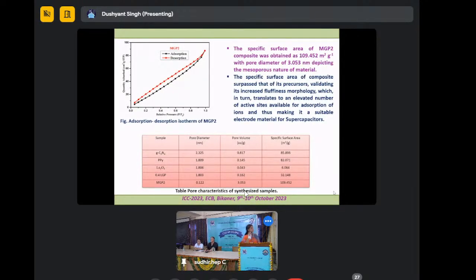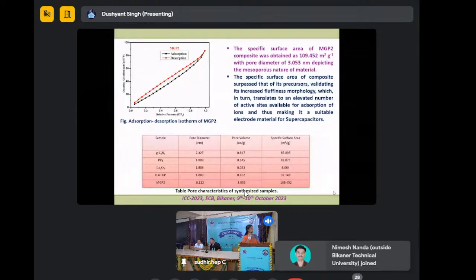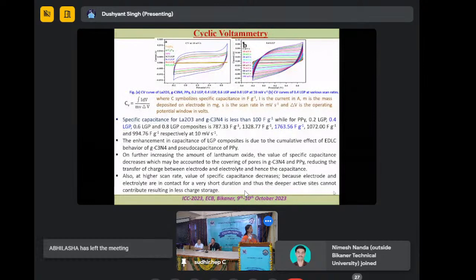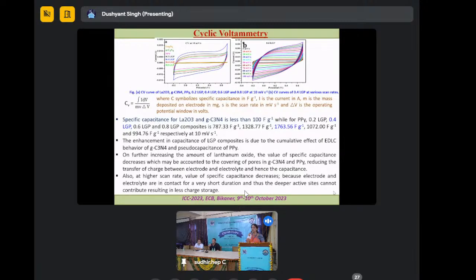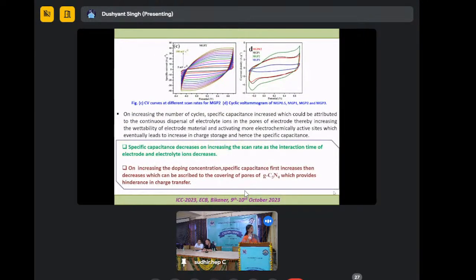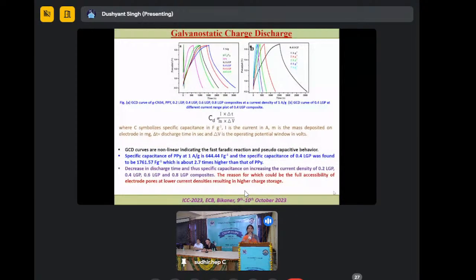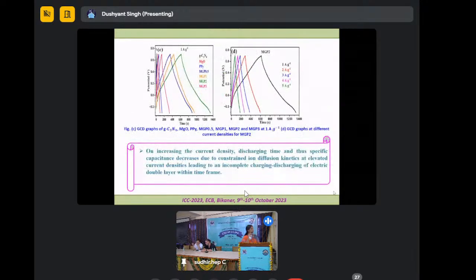A moment. So this table concludes the effect on the surface areas, and these are the main cyclic voltammetry measurements, which show that the specific capacitance of the lanthanum oxide composites reaches up to 1763. Means we can find out that specific capacitance can be increased with the help of doping of these lanthanum oxide materials, and on increasing the doping concentration, specific capacitance first increases and then decreases. So it can be used as a good electrode material, and this is the GCD measurement for the lanthanum oxide